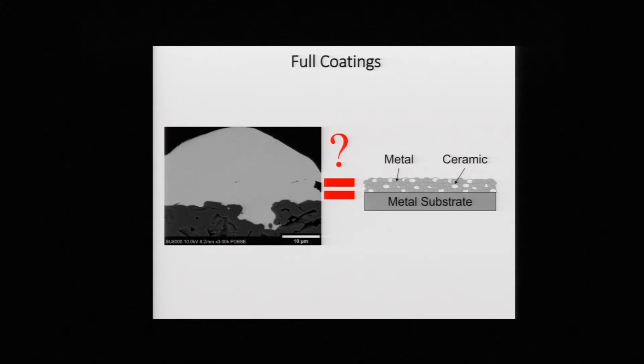But we're actually going to need to go even further than that and see at the atomic scale if there's any chemical interaction to explain why surface roughness has a counterintuitive effect and how the different ceramics play a role in here. We saw that changing the ceramic had an effect on both adhesion strength and on the velocity you need to deposit these. But once we've completed all of this work, we're going to need to think back and see how these single particles reflect in a full metal matrix composite coating. But this work will help us improve those metal matrix composites.